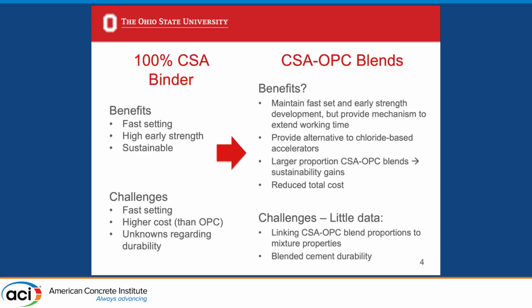Similarly, perhaps going the opposite direction, we could use CSAs in small proportions to provide alternatives to chloride-based accelerating admixtures. So we could get an early set time and early strength gain without adding chlorides to our system. We also, when doing that, can maintain some of the sustainability gains associated with CSA, albeit in a lesser amount than if we use a 100% CSA mixture.